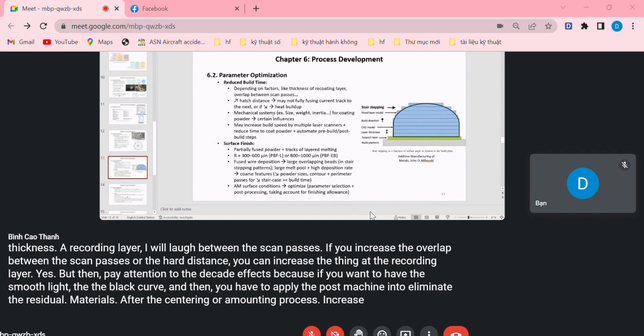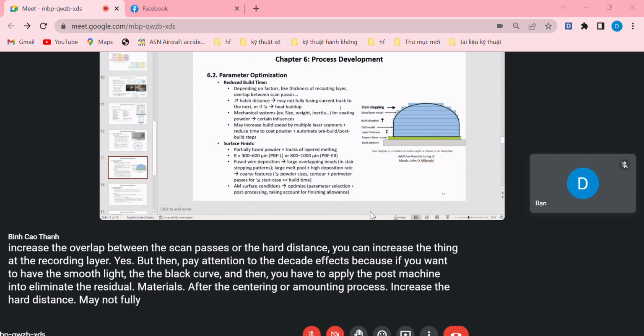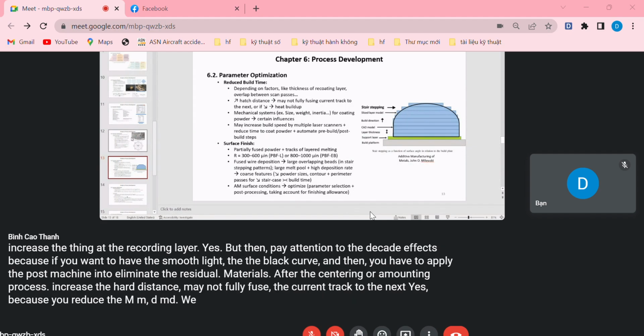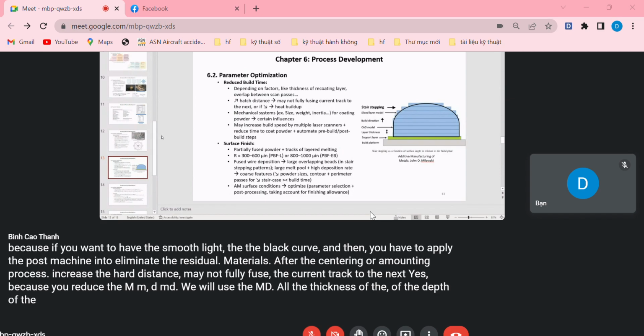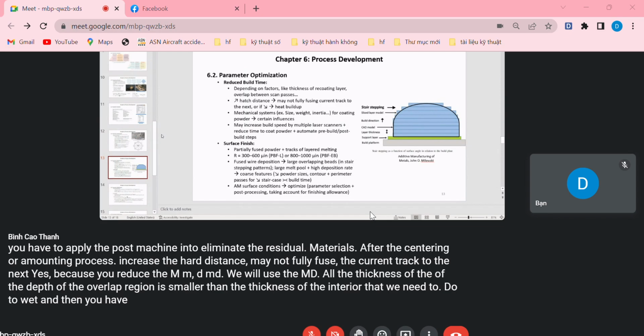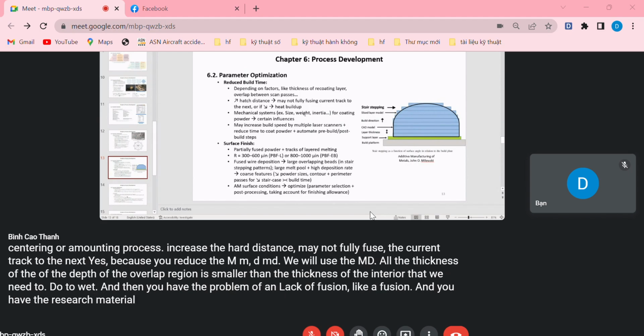Increasing the hatch distance may not fully fuse the current track to the next, because you reduce the MD. Or the depth of the overlap region is smaller than the thickness of the material that you need to wet, and then you have the problem of lack of fusion, and you have the risk of material delamination. So delaminate, sự tách lớp.